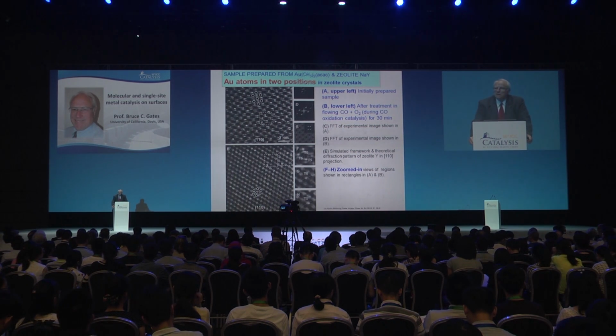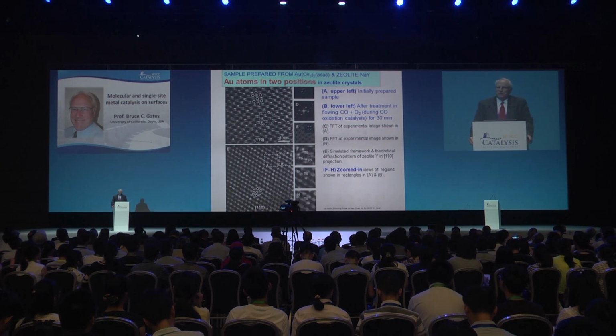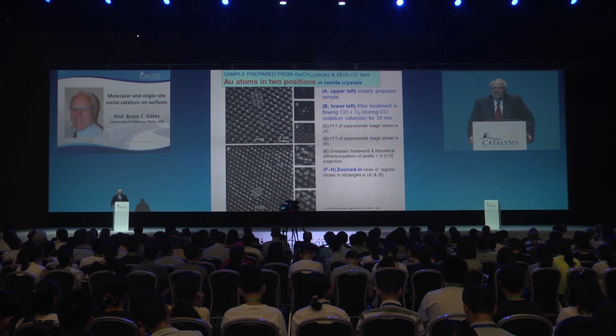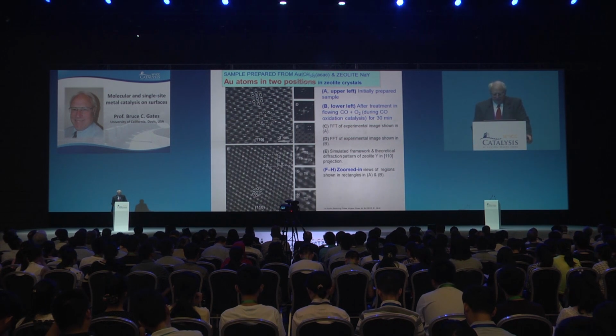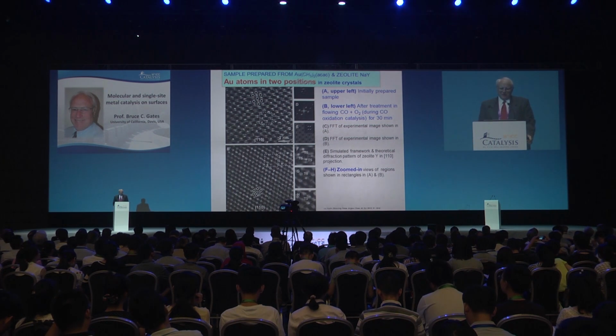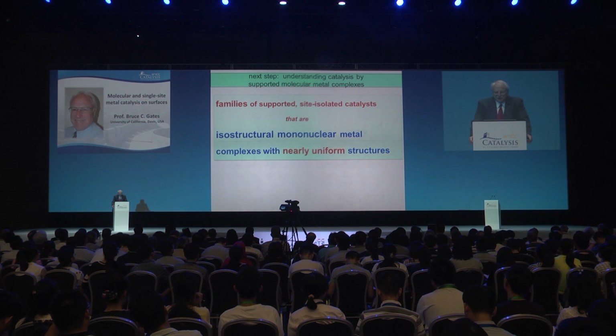But the mononuclear character of the catalyst, the atomic dispersion of the metal, remains. So two sites, not one. I oversimplified slightly, but it's very close to the model kind of catalyst that we're striving to work for.